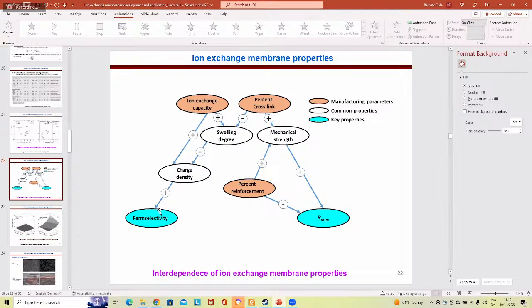Your second question has to do with the stability of the membrane, in my understanding. The stability is really influenced by the amount and the type of functional group that you have inside the membrane. One of the research directions is, for example, when we use anion exchange membrane in water electrolysis to produce hydrogen, we strive to make membranes which are really very stable in potassium hydroxide, because potassium hydroxide is very aggressive and the membrane immediately dies.